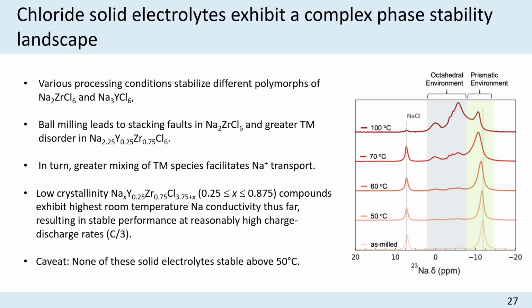Unfortunately, you can't really see this plot, but what you can clearly see here is a change in the sodium NMR data as you heat treat this material to different temperatures. And again, this is showing you that you're changing the crystal structure with even moderate heat treatments at 50 degrees Celsius. So clearly, the recrystallization process is happening very quickly. And it's affecting the conductivity.